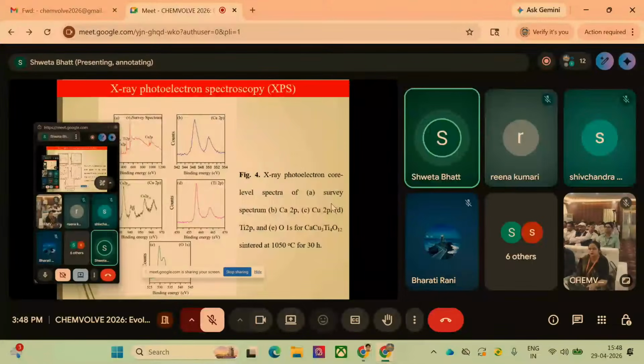In the case of calcium, two peaks are showing at binding energies of 348 and something like 350 eV, so calcium is present in the 2 plus state, copper is in the 2 plus state, and titanium is present in the 4 plus state.